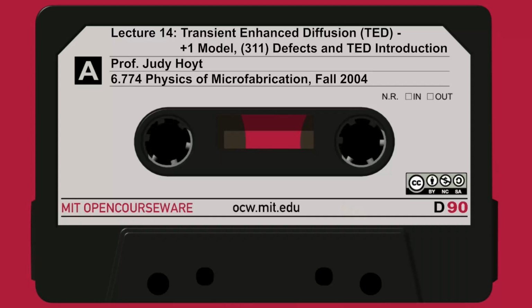So the type of enhancement we're talking about here may only last for a short period, but we're talking about maybe 20,000 times the ordinary diffusivity at 700, or maybe even 400 times the diffusivity at 1,000. So these are not negligible. These are huge enhancements. And there was a lot of work in the early days spent trying to figure out what this could possibly be due to. So let's go on to slide 7.